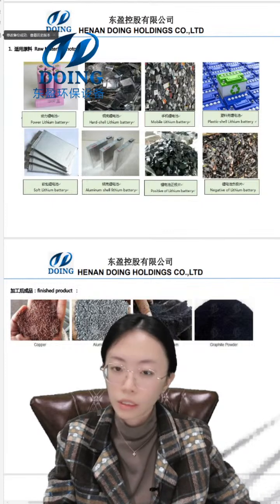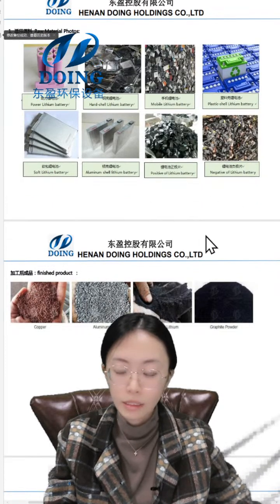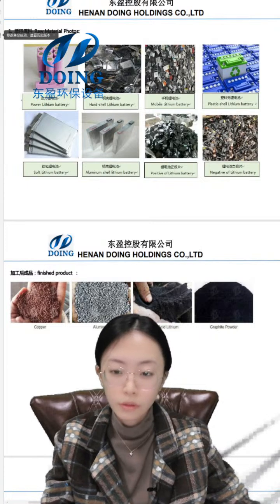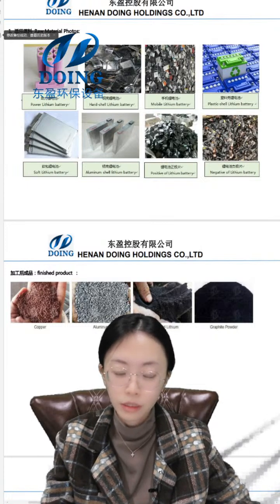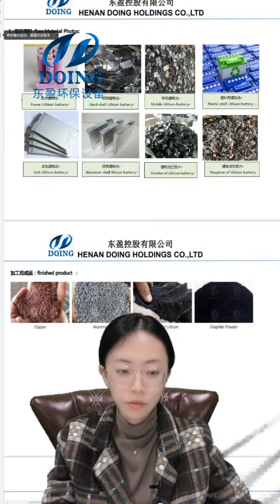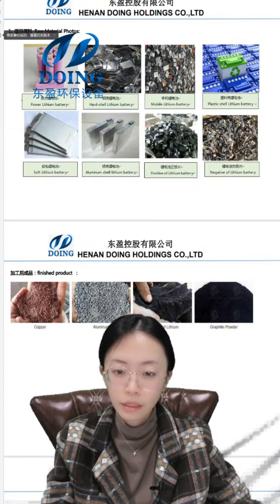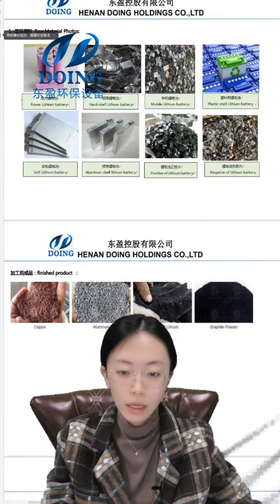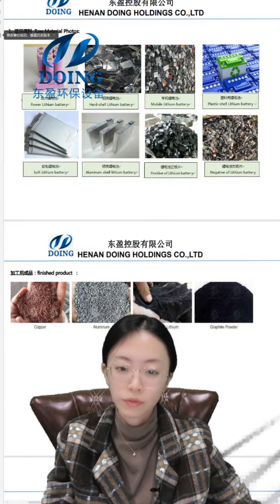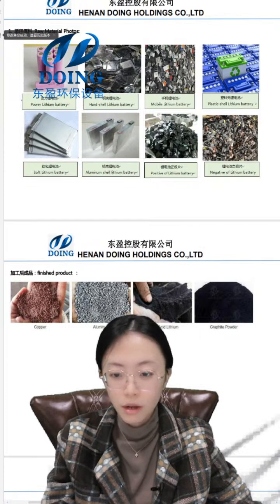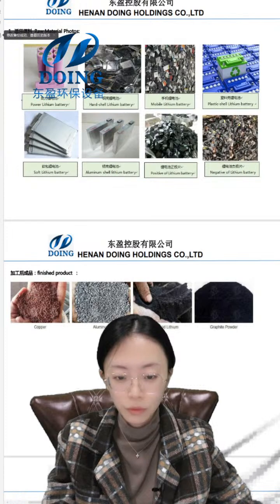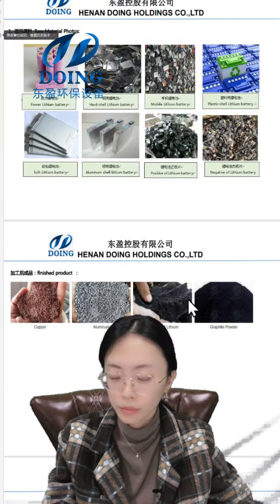From the processing, we can get more than 10 or 15% of copper and 10 or 15% of aluminium. We also have 3 to 5% of iron, and also graphite and lithium iron phosphate. That's the black powder. This is our mixed product.